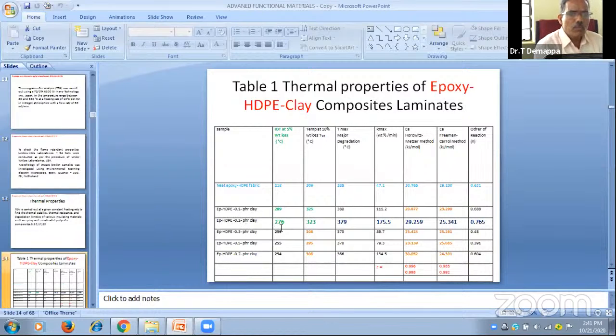Whereas coming to 0.2 PHR, that is 276 degrees centigrade, it decreases a little bit. Then 323, that is 379. You see, it increases still further. That is the rate of degradation, the temperature required increases. Here the energy of activation increases a little bit. Here also it increases. The order of the reaction is 0.765. At 0.3 PHR it decreases. After 0.2 to 0.3 onwards, it decreases. Here also, after 0.3 PHR, it decreases. Here also the energy of activation decreases.